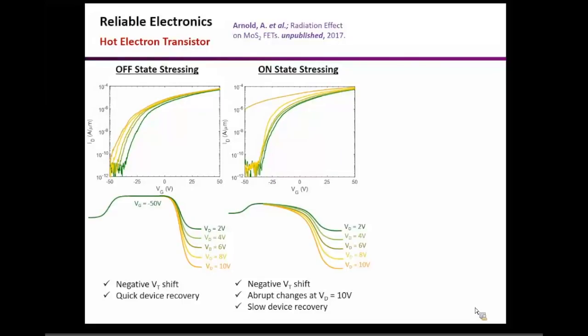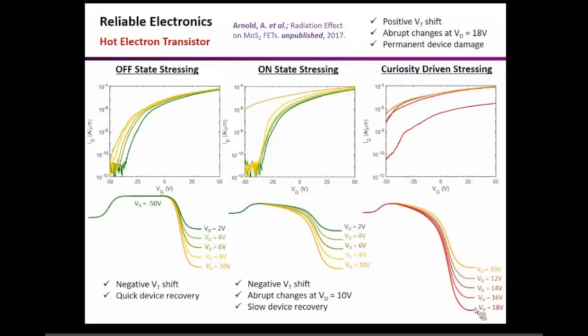But then the next step is something we call the curiosity-driven stressing. We still didn't stop. The device was almost like not working, but we still kept increasing this drain bias. And then we found something abrupt happened again at 18 volts, where the threshold now shifted from very large negative to very large positive.